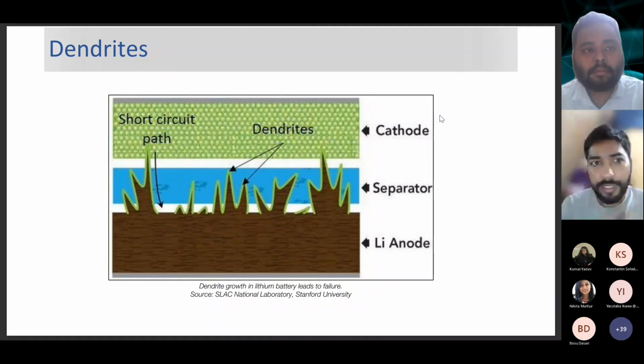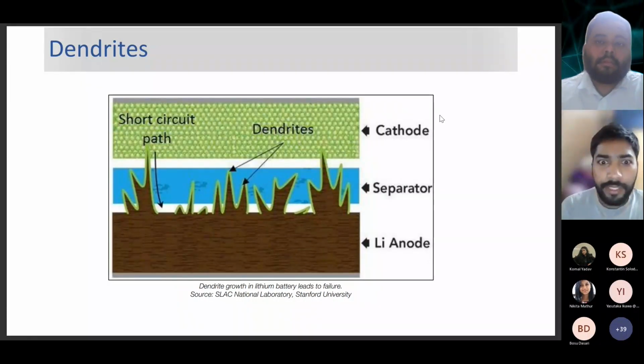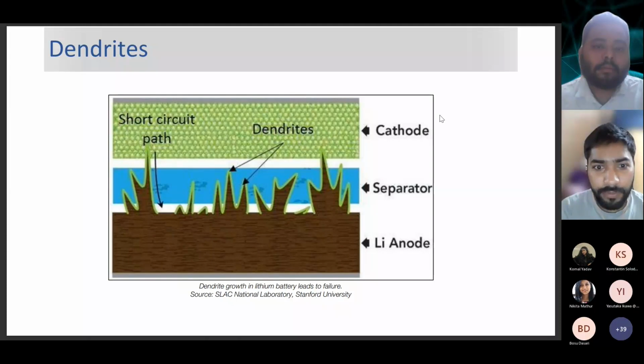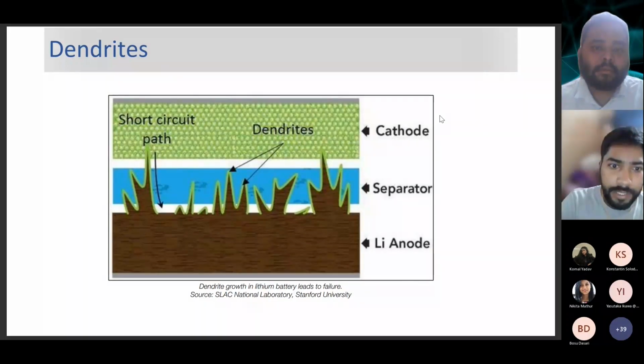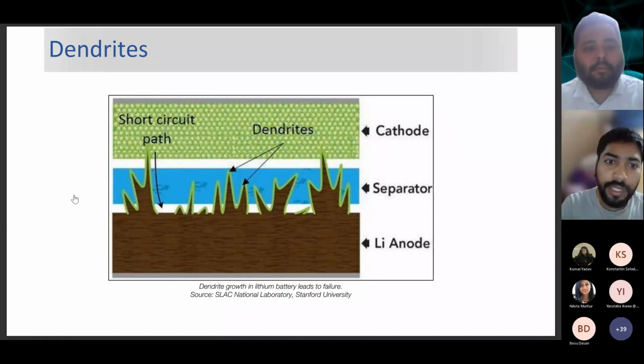So in the last slide, we saw a mention of dendrites. I think it was Vani who mentioned it. Looking more into it from a pictorial perspective, assume this is an anode and this is the cathode side, and in the traditional cells we have a separator in between and liquid electrolyte. Over a period of time, the lithium metal starts growing out in a root-like structure like this, and eventually it penetrates the separator, travels further ahead and touches the cathode part. When this path is connected, it is basically an internal short circuit, and this may lead to cell failures, and in some cases thermal runaways, where the cell catches fire.